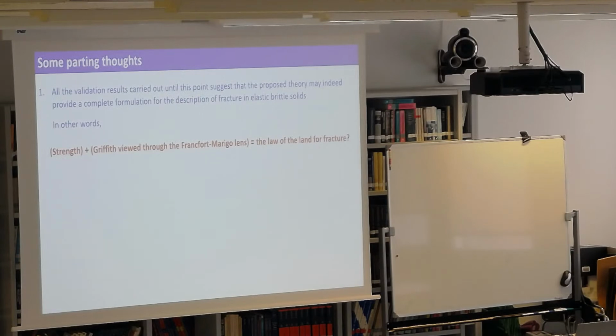Of course, we need to do more things, more validations. We need to understand more. But, I mean, given what we have seen so far for these very different problems, this is very compelling and very encouraging. We are now looking at things that are not elastic. We have a lot of experiments, in particular elastomers, that are viscoelastic. So you now have a system where you have dissipation, not through just creation of surface, but you have dissipation in the bulk through viscous deformation. And we are not there yet, but what we have done so far suggests that this still applies, okay? So these equations are very good equations.